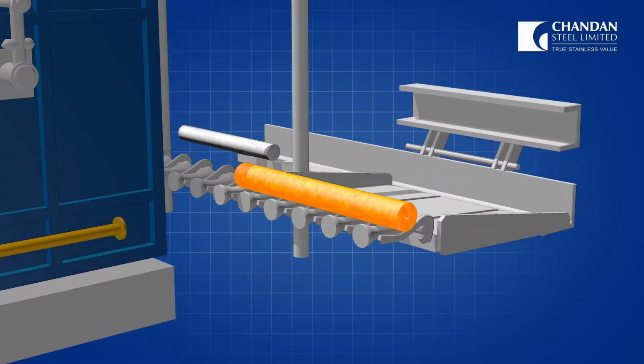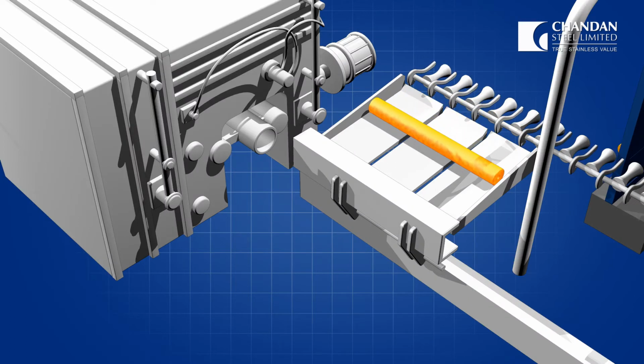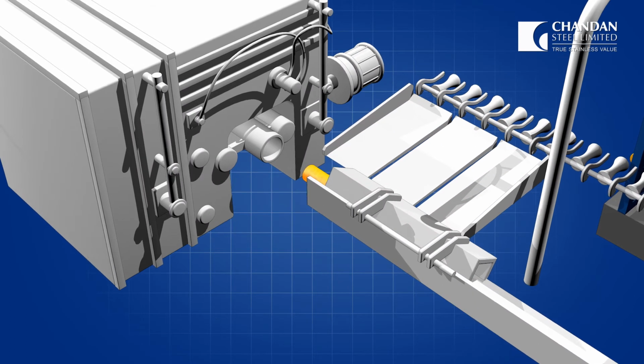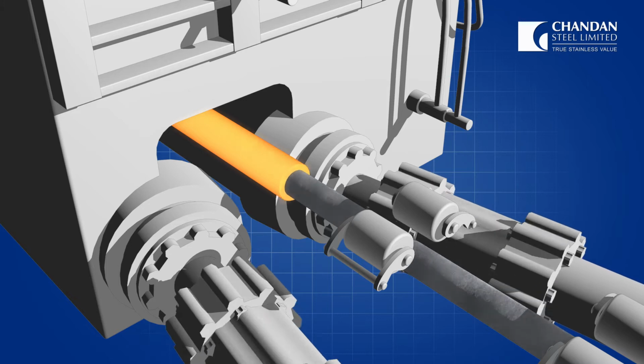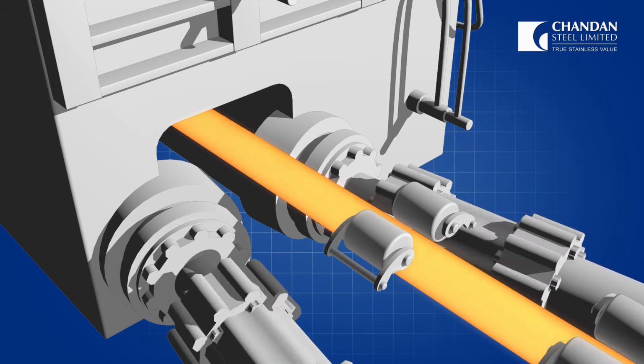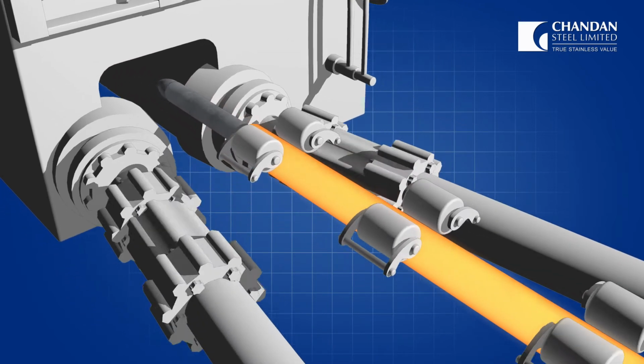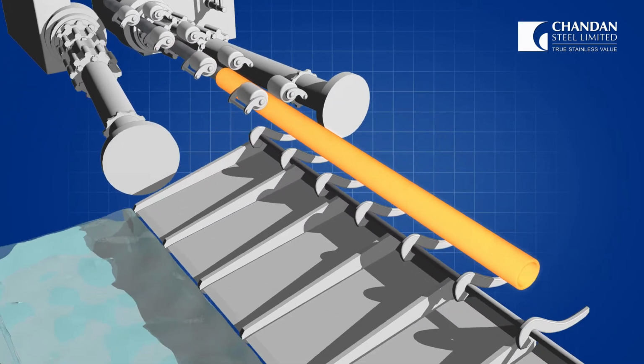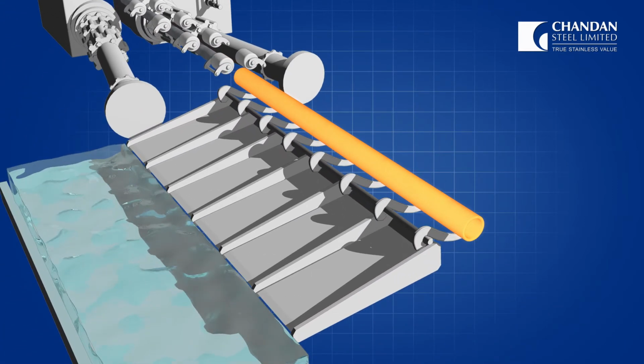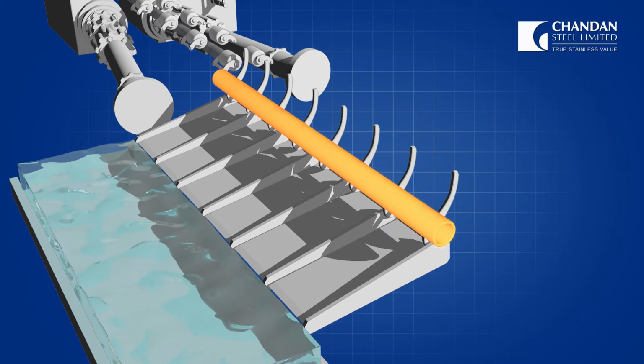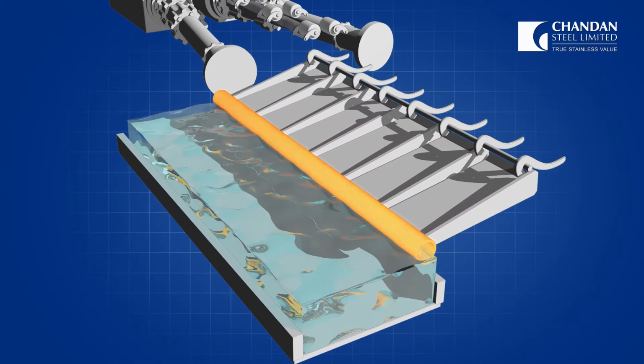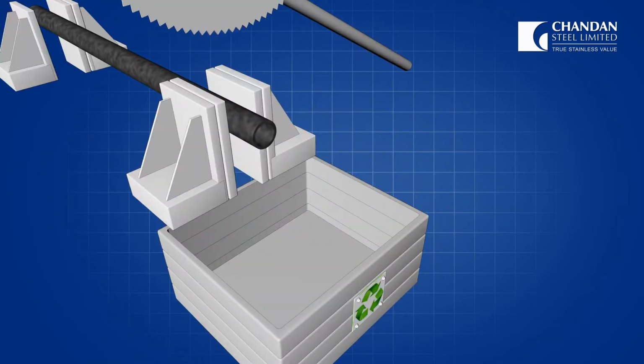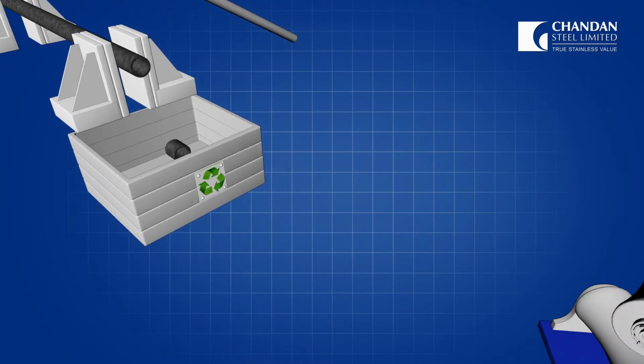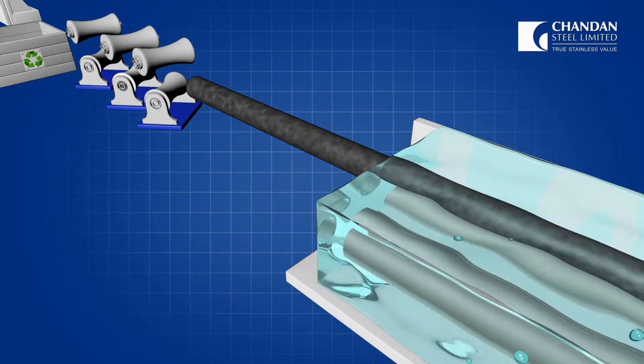Use of glass lubrication for outer and inner diameter of bars minimized surface torsional and circumferential stress deformation with use of molybdenum plugs result in improved surface finish of the product during the indigenous hot piercing process adapted by Chandan Steel. The pierced hollow bar is cut, straightened, pickled and ground if necessary for any surface imperfections.